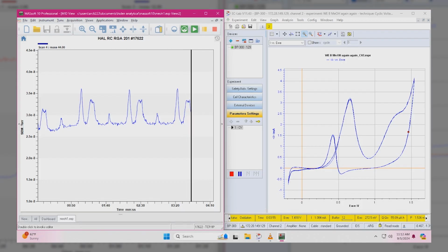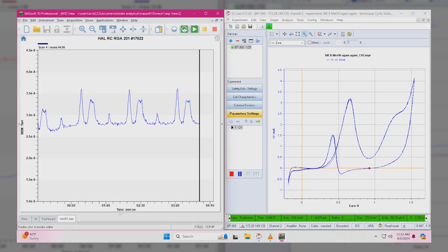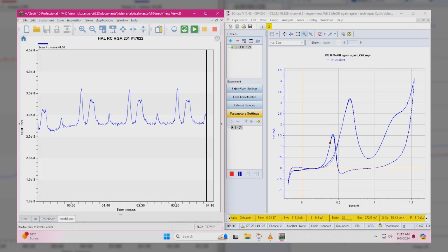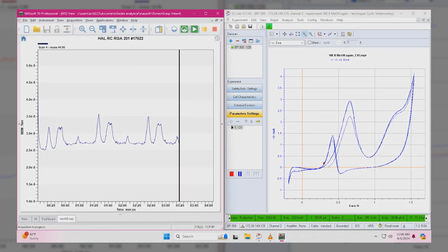And now we're going to scan in the reverse direction, or cathodically, and we're going to see platinum reduction, and then a reverse scan methanol oxidation wave. Because methanol oxidation occurs at these potentials regardless of the direction of scan. But you can see that the forward scan gives a much higher current response than the reverse scan. So this is just a view.